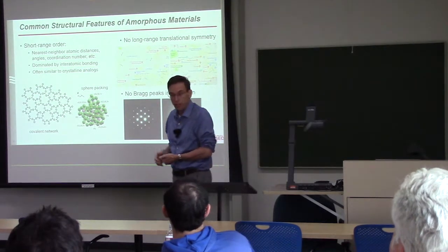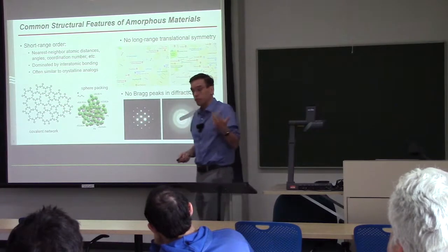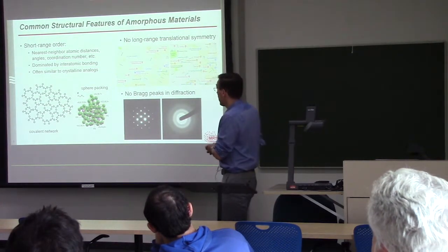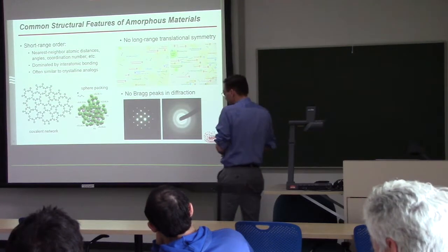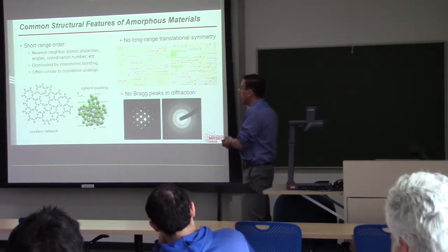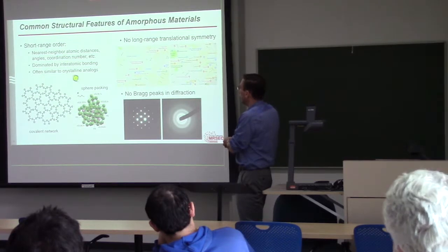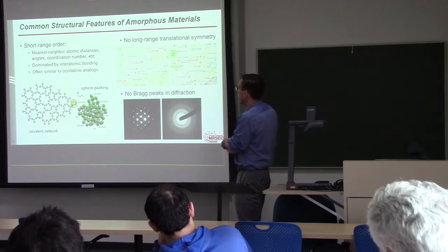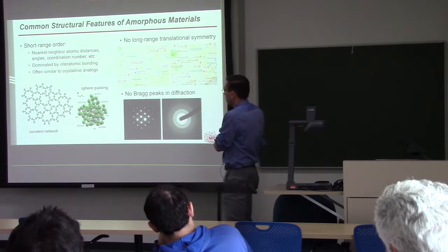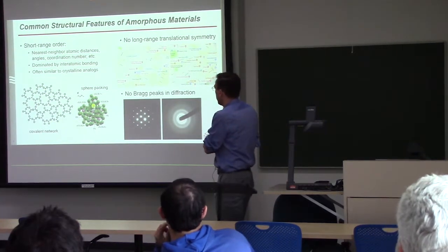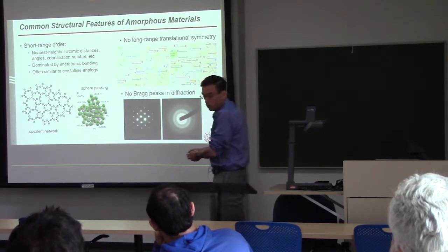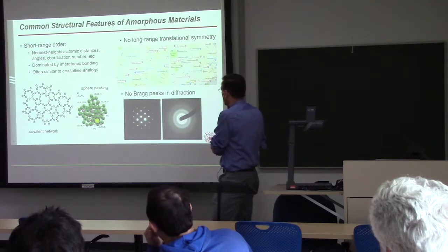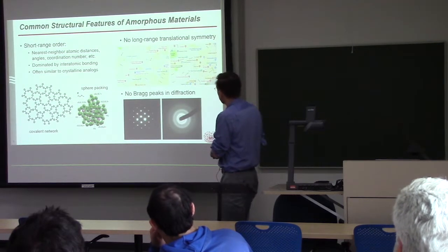So if you have, for example, a metal that prefers a certain number of nearest neighbors, you may find a very similar number of nearest neighbors, at least on average, in the amorphous form. If you take care of bonding issues, you may form networks that locally satisfy bond angle issues, or in metals you may have to create local structures that satisfy not only the bonding, the nearest neighbor numbers, but local electronegativity considerations as well.